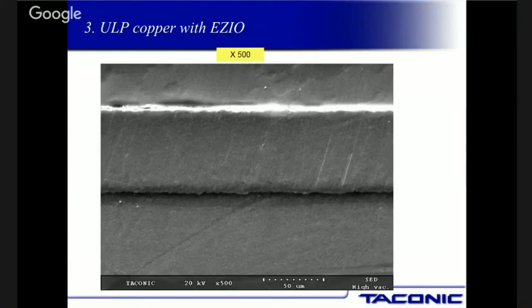And so we have been able to attain 4 to 5 pounds bond strength. And I have another slide on my computer, but we have boards that we've built with 2 mil lines and spaces across a 24-inch board, and they all stayed on the board. And again, 2 mils is pretty small lines. Now you guys never will try to attain that, but when you start looking at the high-speed switching industry, where Yahoo and Google want very fast signal propagation, they want very, very small lines so they can do a lot on their boards. And so they're looking at very smooth copper. We can actually hold the 2 mil lines and spaces across very large panels without the copper coming off.